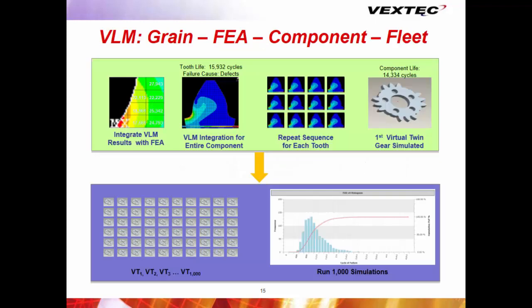And so, kind of how that works is you can take your finite element model, and at each element in your FEM, you find a life for that element, and then you look at the other elements, and that can roll on. But the important thing is you get down here to the end where you've simulated many of them. You can start to simulate what do I expect to see in a fleet of these. So if I make 1,000 of these, when do I expect the first one to fail? But the other important thing is, if you're using, which you are in this room, if you're an FE-Safe user, can I use this to take a small amount of test data and simulate a large test program?